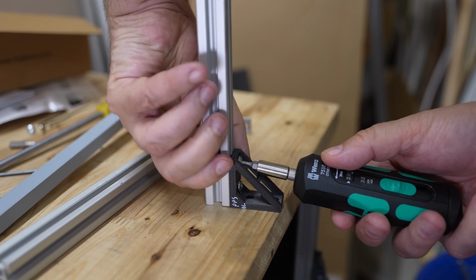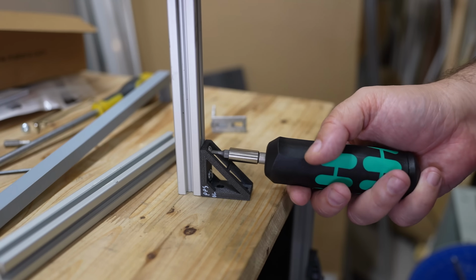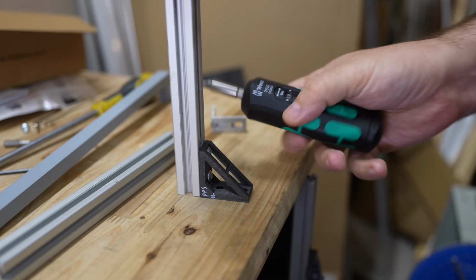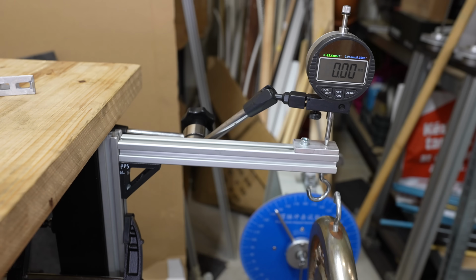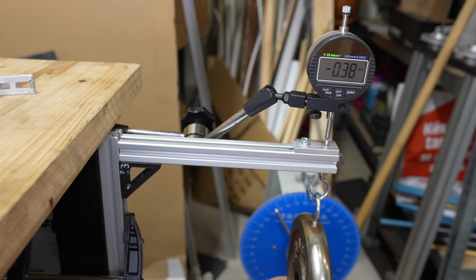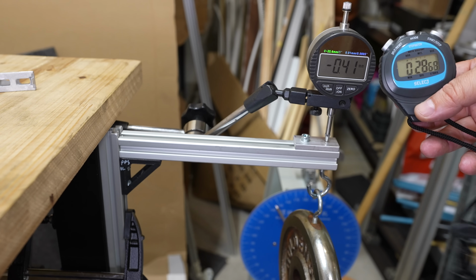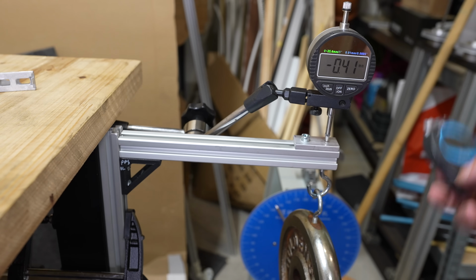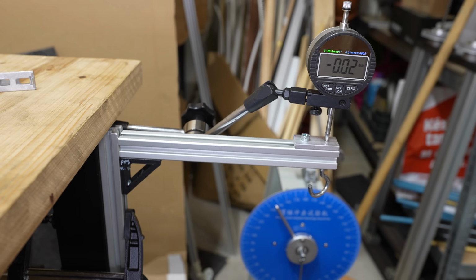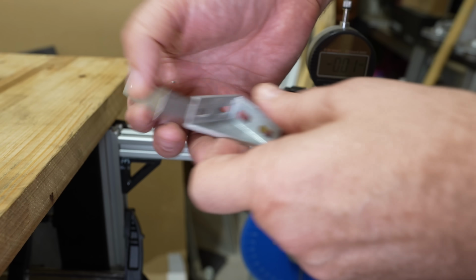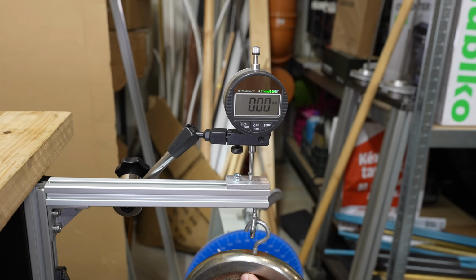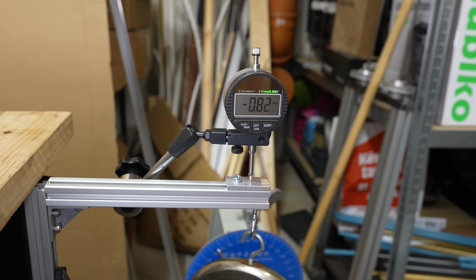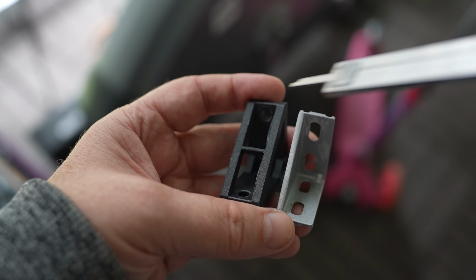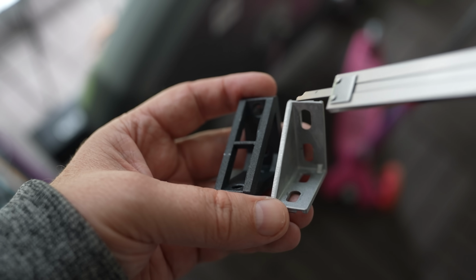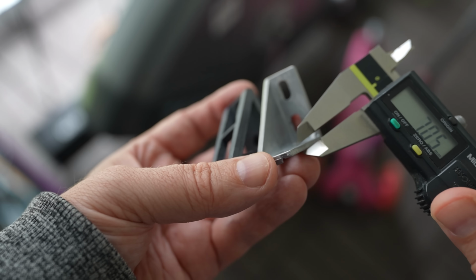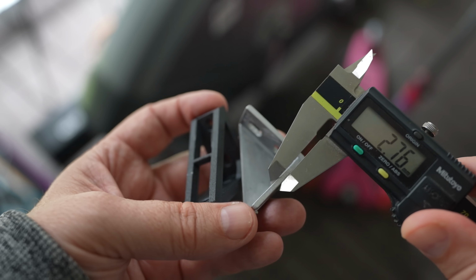And now that bracket test from my PET-CF comparison video, and this time I'm using the torque wrench set to 1 Nm. The load will be 2.5 kilograms at exactly 200 mm distance, and deformation is slightly smaller compared to the average PET-CF. In that video I included this aluminum bracket, but it has only one bolt on each side. In the meantime, this one arrived, still aluminum, and it is better, but interestingly, not as good as the 3D printed versions. Still not a fair comparison, because the 3D printed bracket has supports from two sides, and this one only on one, and it is thinner. But it is good to be familiar with the possibilities.